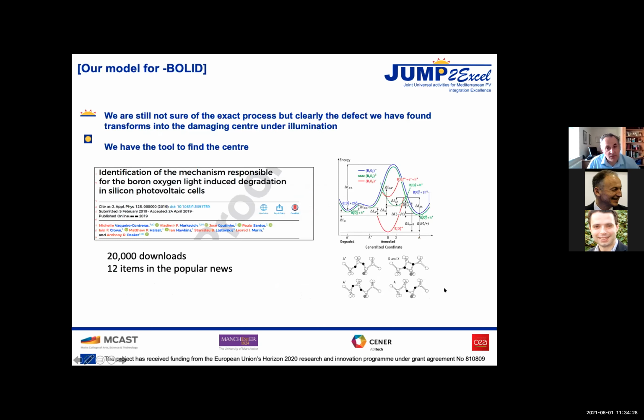And then we turn to theory. So we turn to our friends in Portugal, and they found a stable defect that would behave like this. And it actually has four states, two of which are degenerate, so we don't see a difference between them. And one state is indeed a deep donor, which is the one we see, and when the Fermi level changes, when you illuminate it, this will convert to a damaging state, which is one of these states. And that's actually a shallow acceptor.